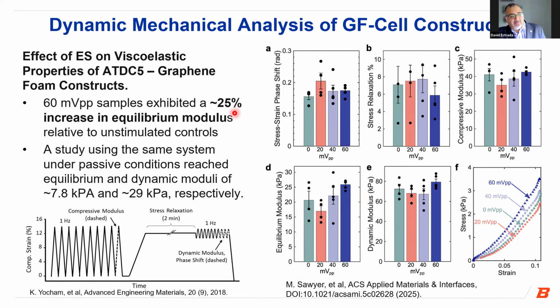But really what we did is we then went back to a paper we published in 2018, and we noticed that for the equilibrium and dynamic modulus, where we didn't submerge those ATDC5s and graphene foam in the cell culture environment and they had no electrical stimulus, the equilibrium modulus was only about 8 kilopascals, right? So we're about a factor of 3 better on that. And the dynamic modulus in that was only about 29 kilopascals. So we're about a factor of 3 improvement there as well with the electrical stimulus.